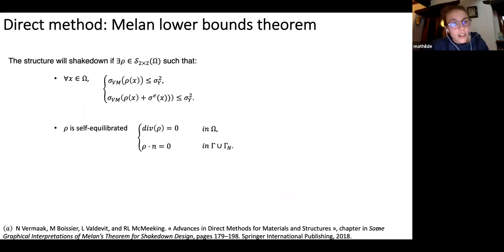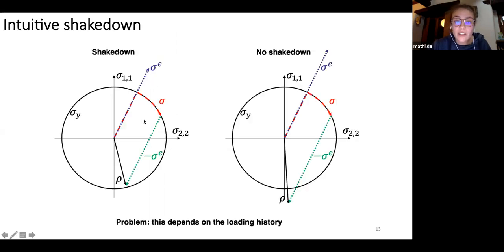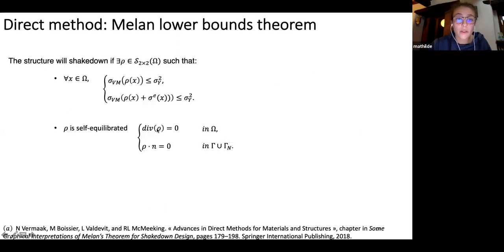But actually, we can characterize shakedown through direct methods, and especially Melan's lower bound theorem, that says that a structure will shake down if there exists a stress rho such that this stress remains in the circle, so it satisfies the van Mises condition, and this stress plus the ideal elastic stress remains in the circle. So that's exactly this case here. The stress is in the circle, and the stress plus the ideal elastic stress remains in the circle. And this stress has also to be self-equilibrated. Indeed, when we unload, we don't have any loading applied on the object, and it has to be a stress, so it has to satisfy an equilibrium equation.